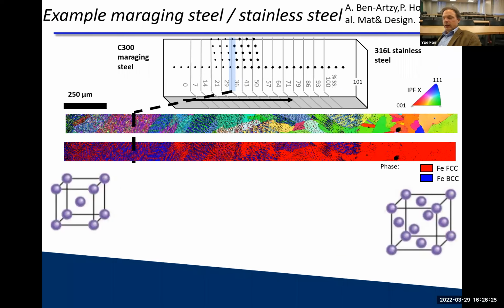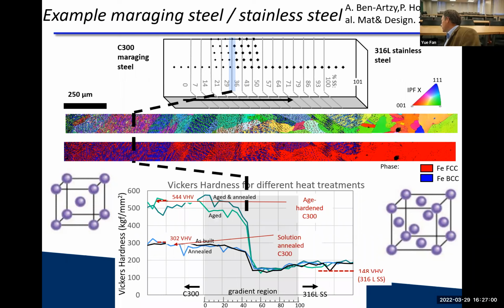And so when we print these things layer by layer, afterwards we do a cross section here and look at the EBSD in this instance. Blue is BCC, red is FCC. Those are the orientations. As one may expect, if you go from a BCC to an FCC material, you get a mixture of the two, and somehow in a gradual way. When we pick a specific location here, we can then plot the hardness. Now we may expect that because you have a continuous mixture of FCC and BCC, the hardness gradually changes as well. Well, it turns out it doesn't. The hardness actually changes very abruptly. And exactly at one compositional change layer, you have a steep drop in hardness. It's not a gradual thing like the mixture may suggest.